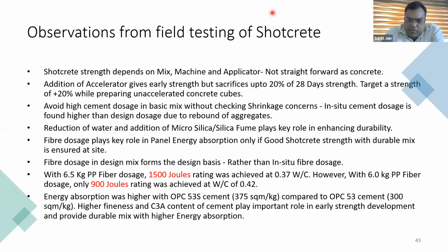Now at our site, we used 6.5 kgs of PP fiber. We achieved a maximum of 1500 joules at a 0.37 water cement ratio. But the same thing dropped drastically from 1500 to 900 joules when we increased the water cement ratio to 0.42. And this was only with a marginal reduction in PP fibers. We were still using 6 kgs, which was not very much less than 6.5 kgs, but the energy really went down.